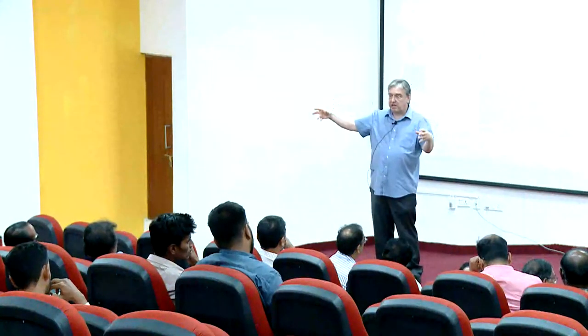I think we have to say there is an important difference between equilibrium thermodynamics, where the system goes from a stable initial state to a stable final state, which can be quite well understood by thermodynamic models. But in metals, very often, we deal with non-equilibrium processes. So you start, at best, from a stable initial state, you do something, and you end with a state which is far out of equilibrium. There, thermodynamics is not going to teach us the evolution laws of such a system. That is the main roadblock.